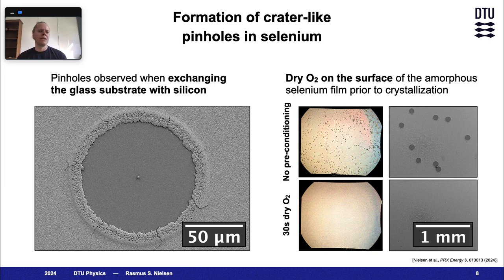The way in which we mitigated the crater formation was by dosing dry oxygen onto the surface of the absorber for 30 seconds immediately before the thermal annealing process.